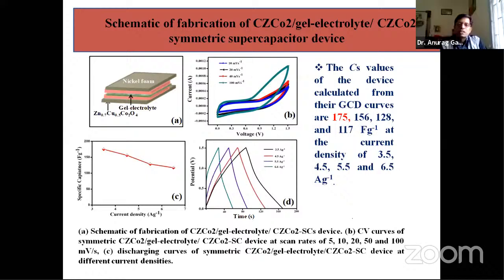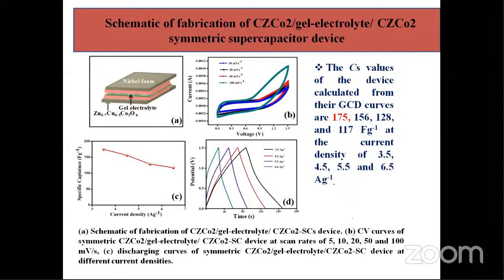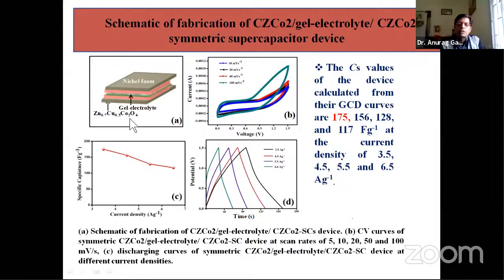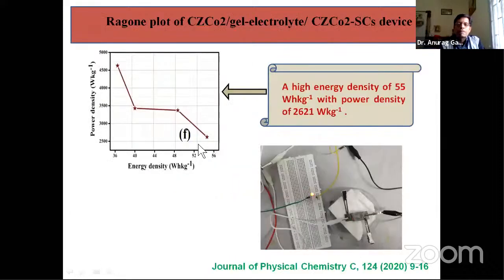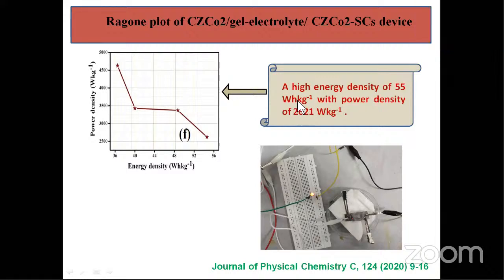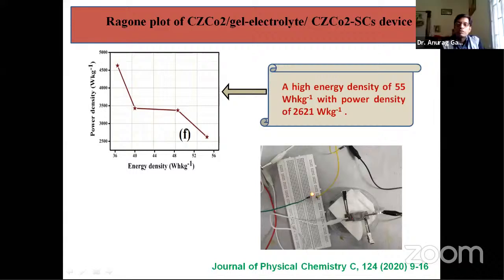And then you can see the symmetric fabrication of another device, the zinc cobalt copper oxide, again with gel electrolytes. So with this we have gone through all the CV measurements and specific capacitance values, and finally we tested the energy density and power density. The energy density for this device is 55 watt hour per kilogram. This is improved further, as previously it was 39, but for this composition it is around 55 watt hour per kilogram with a power density of 2621 watt per kilogram.